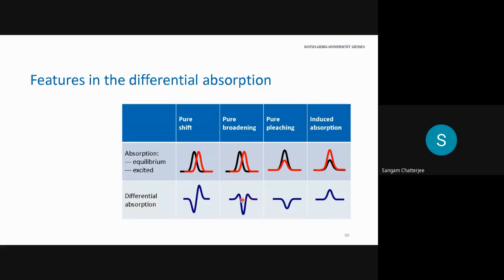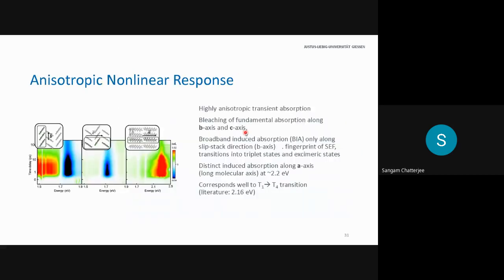And if you analyze this very carefully, the areas which are above the zero line here and the area below the zero line are the same. If you have loss of oscillator strength or loss of area, you get a bleaching. And this bleaching is a purely negative system. And you can also have a purely positive system, which is induced absorption. So if you excite a system, it can show more absorption than it did without. And of course, in real life, you don't have narrow resonances and you don't have the pure effects, but you have combinations of these. And let's see what happens in this crystal system that we have here.